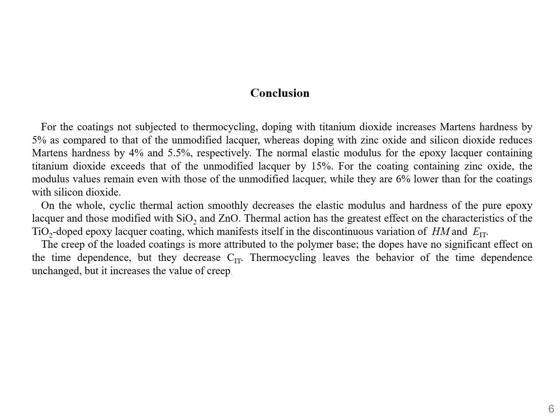For the coatings not subjected to thermocycling, doping with titanium dioxide increases hardness by 5% as compared to that of the unmodified lacquer, whereas doping with zinc oxide and silicon dioxide reduces hardness by 4 and 5.5% respectively. The normal elastic modulus for the epoxy lacquer containing titanium dioxide exceeds that of the unmodified lacquer by 15%. For the coating containing zinc oxide, the modulus values remain even with those of the unmodified lacquer, while they are 6% lower than for the coating with silicon dioxide.